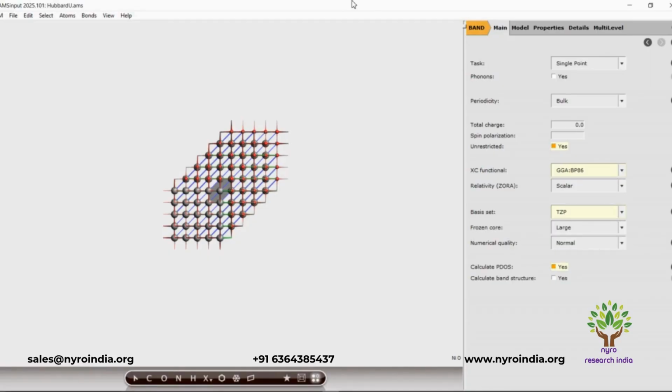And with Hubbard, the partial density of state from a DFT plus Hubbard calculation of NiO will show significant differences, for example, splitting of nickel 3d states. The Hubbard term will split the nickel 3d band into a lower Hubbard band, occupied, and an upper Hubbard band, unoccupied, separated by an energy gap. The size of the splitting is related to the value of Hubbard U. And the band gap character, obviously the partial density of state will clearly show.